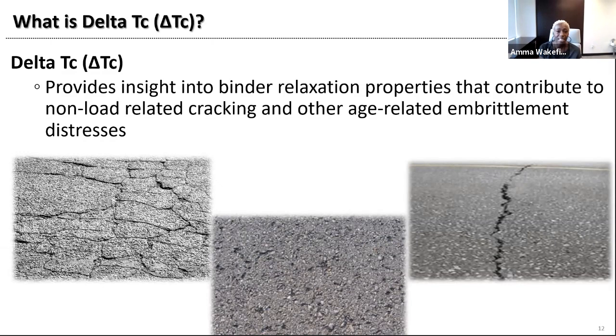So what is delta TC? Delta TC is an asphalt durability parameter that was talked about by Mike Anderson and Phil Blankenship in a paper in 2011 at AAPT. This parameter can be determined by conducting tests that are typically done on binders in the PG grading system, if you do the full grading. So in a way, it's an attractive option, because some agencies don't want to have to add yet another test to their matrix if they don't have to. So if there's an opportunity to get more information by analyzing the data you're currently collecting in a different way, then that's advantageous. And that's kind of how delta TC is playing out.